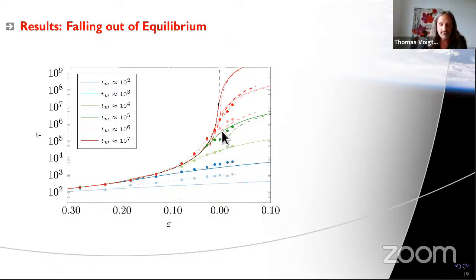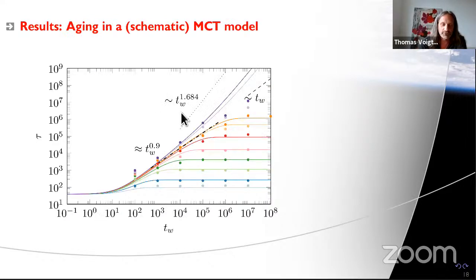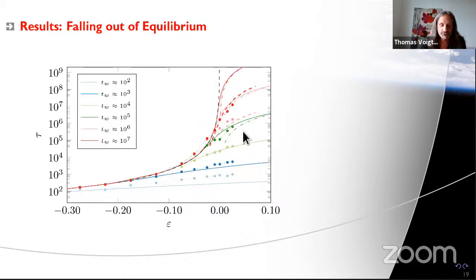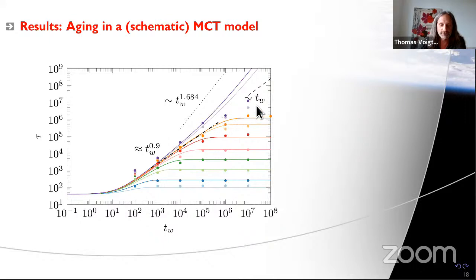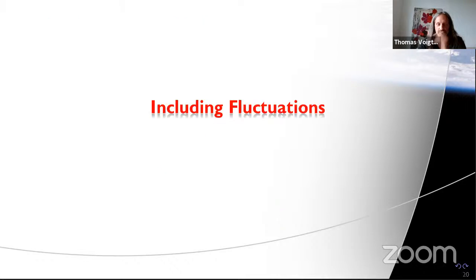And the colored lines are my hybrids using a schematic mode coupling theory together with Magdaleno's non-equilibrium aging results. And it's the same fit that I was using here. So it's just that in a different representation, you see deviations differently. So I'd say this looks very convincing. I can even calculate asymptotic behavior for the shape of the curve here. The only problem is that if you look closely enough and you're not colorblind, you realize that the dark red here should actually be up there, and these pinkish reds belong together. And it's the same problem that we encountered here, that at some point the prediction of the theory is far larger than what is actually measured. So we need to come back to this.